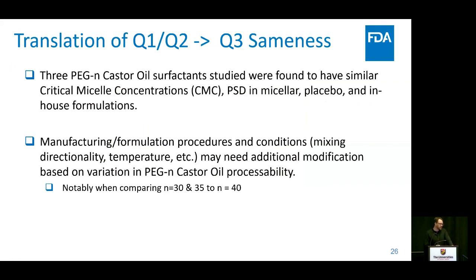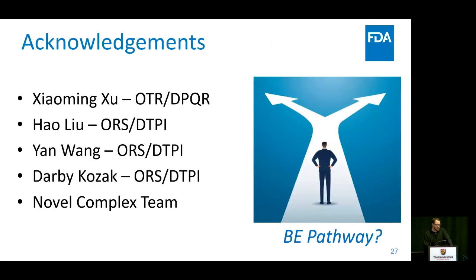So in conclusion, what we showed was that for all three of the PEG castor oils, they had similar Q1 properties: CMC, the particle size for the micelles, the placebo, and the in-house formulations. And when you're using these different surfactants, you have to keep in mind manufacturing and formulation procedures and conditions as far as mixing directionality, temperature, et cetera. That's especially true when you're looking at the flowable ones versus the non-flowable ones. So with that, I think that's my whole spiel here.